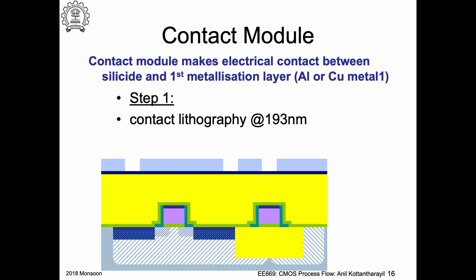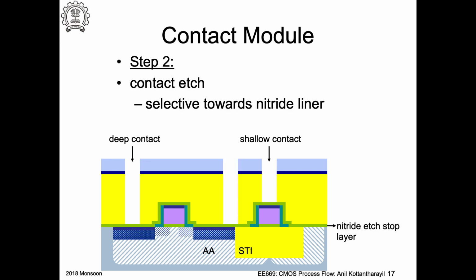So you do a lithography, right? And the top layer is actually photoresist. So this is after development of photoresist. Then you're going to etch your liner oxide and the phosphosilicate glass, okay? And the silicon nitride, now you see the role of it. It actually acts as an etch stop layer.